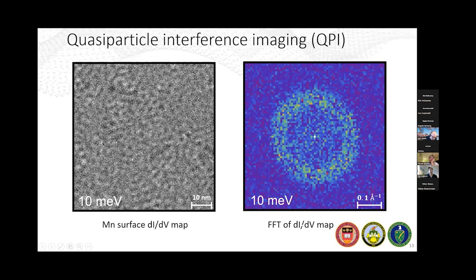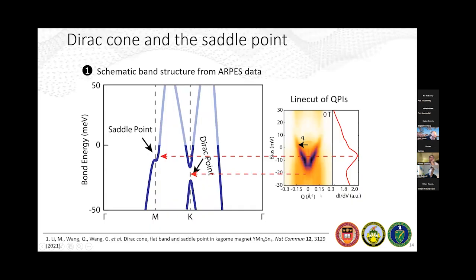And we can span, you know, a substantial energy range, at least for the purposes of STM, that crosses the Fermi level. The summary of what we get from STM is shown here on the right. In the color plot, I'm showing the angular average of the Fourier transforms that I showed on the previous slide. You can see something that looks like a Dirac cone. And here is a dI/dV spectrum.